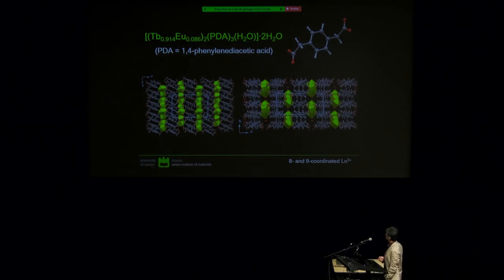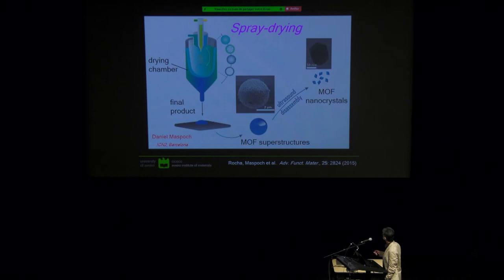To give you an example, we just took some metal organic framework from the literature. We did not make it ourselves the first time. That's the structure. I won't detail it, but basically you have the metal ions again, and the molecule is here, building up the structure. And this was done by spray drying in collaboration with Daniel Maspoch in Barcelona. That's a very convenient way of making this, because you can make large amounts. You can scale it up.